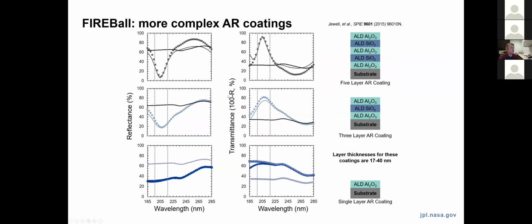And then another application example is the Fireball balloon instrument. Here we considered more complex multi-layer coatings to optimize response in a wavelength range centered near 200 nanometers. So looking here at measured and the expected model performance of single layer, 3-layer, and up to 5-layer AR coatings considered on this mission. Early in the development of this particular project, up to 11-layer coatings were actually fabricated and tested.